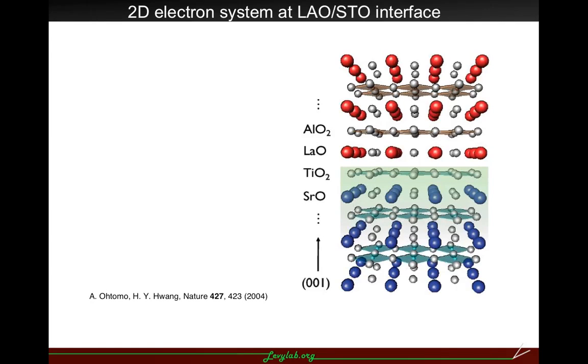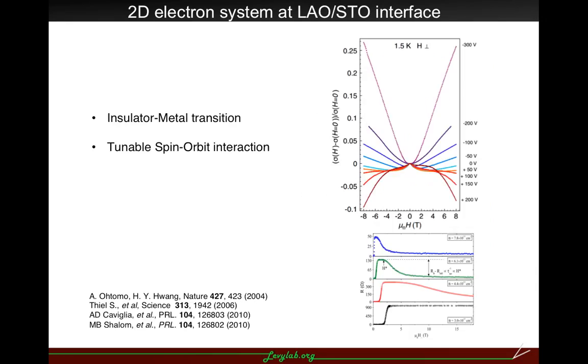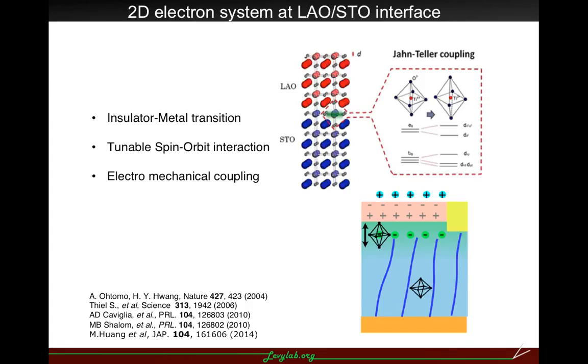Both lanthanum aluminate and strontium titanate are insulators, but when we put these two materials together, a 2D electron gas will form at the interface. The conductance of the interface can be tuned not only by the thickness of LAO, but also the top gate and back gate electrodes. By applying voltage, the interface will undergo an insulator-metal transition. Many of the properties, such as spin-orbit interaction, electromechanical coupling, as well as magnetism, can be varied by changing the carrier density at the interface.